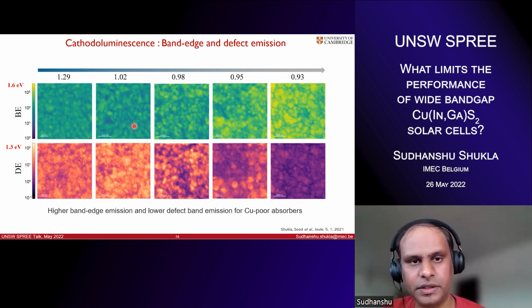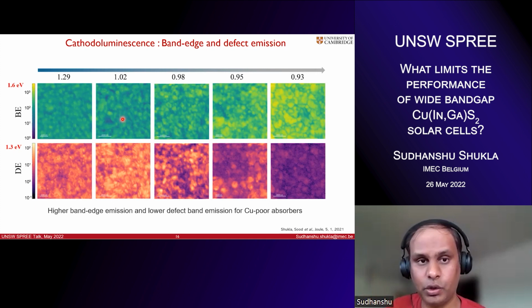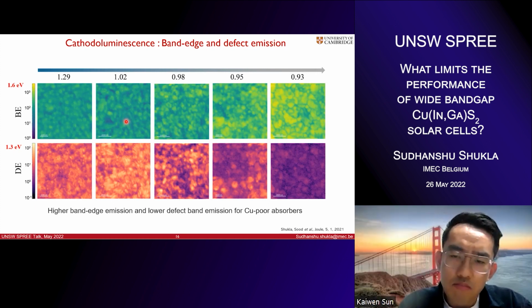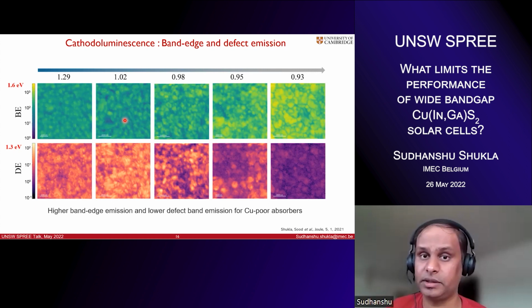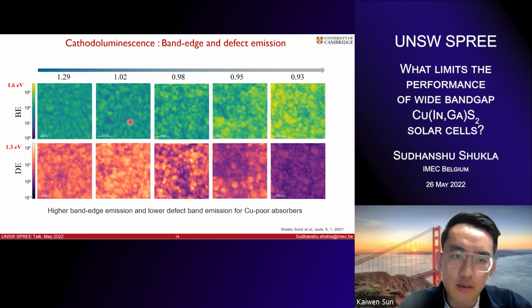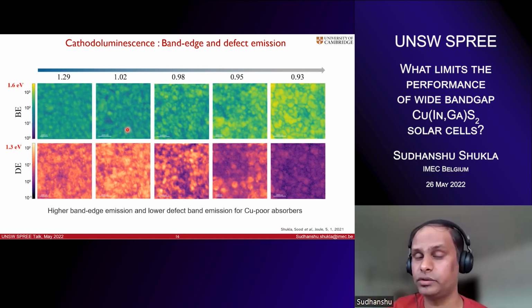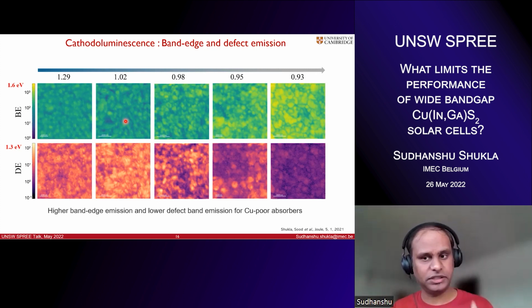So actually, an extension of this study, what we have done is looking at the line profiles in the cathodoluminescence. When you go from one grain to the other grain, you see a shift in the CL spectra. You have a lower band gap emission, or lower band edge emission, coming from the grain boundary, which we think could be due to inhomogeneities, or it could also be from the tail states at the grain boundaries, which could be resulting in the red shift of your CL spectra. This is the observation we have so far. After quantification, we think it's both. You cannot rule out the inhomogeneities, because there could be gallium somewhere high, somewhere low, which could be giving these shifts. And there could be these tail states because of the high compensation.